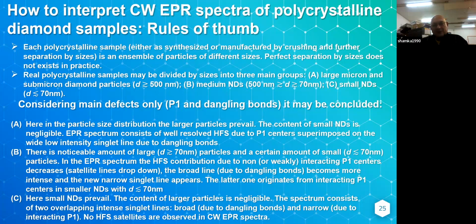In the third group of small, really small nanodiamonds, the distribution is very different. It centers at smaller sizes, and you have practically no larger particles. The content of larger particles is negligible. The spectrum consists of two overlapping intense singlet lines. One is broad, and it originates from the dangling bonds, and the narrow line originates from P1, but interacting P1. No hyperfine split satellites are observed in these EPR spectra. This situation was described previously in the literature.